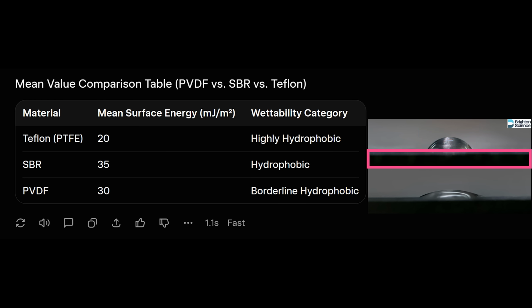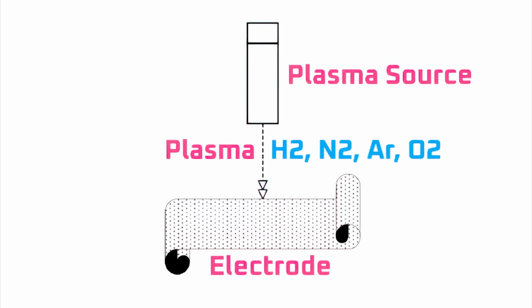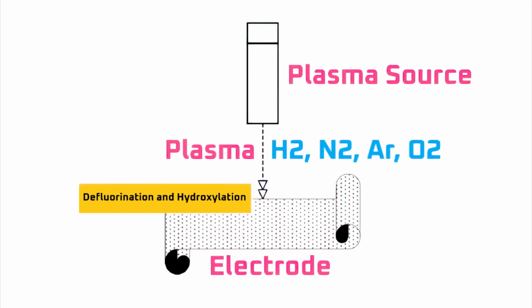But wouldn't the PTFE bonds throughout the volume of the electrode need to be disrupted to allow wetting, not just the surface? No, because as long as the surface bonds are disrupted, capillary action does the rest and draws the electrolyte through the electrode. Tesla's solution to disrupt the bonds, or in their words activate the binder, is to use a plasma made from hydrogen, nitrogen, argon, or oxygen gas. That results in defluorination and hydroxylation at the electrode surface.